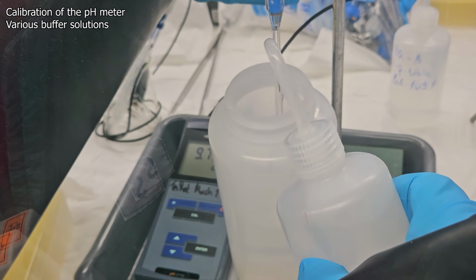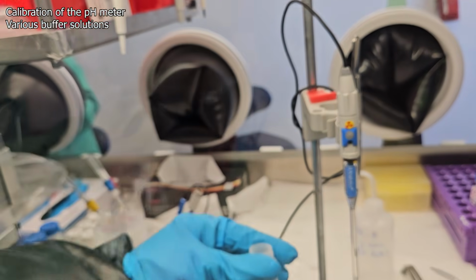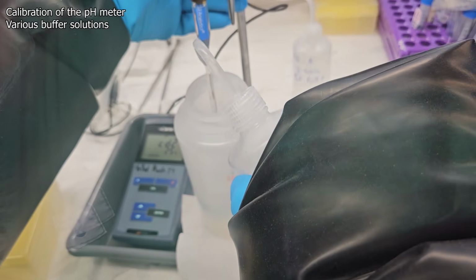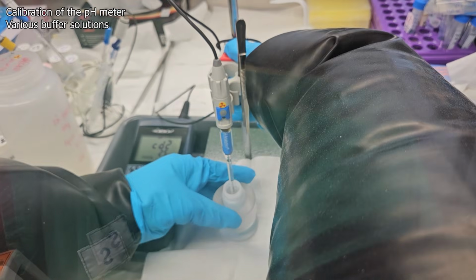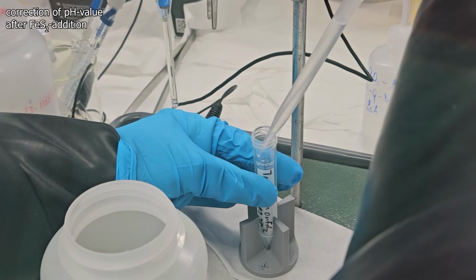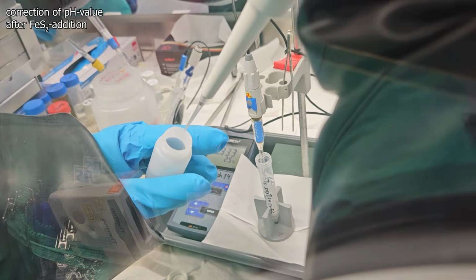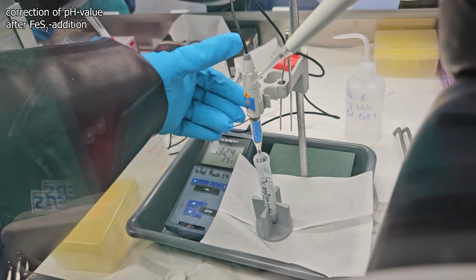In this case, we first want to collect data for just one pH value. To do this, the pH measuring probe is calibrated again. This is done with various buffer solutions of a well-known pH value. The pyrite is placed in deionized water and shaken well. This affects the pH value, and accordingly the pH value must be corrected to the desired level.